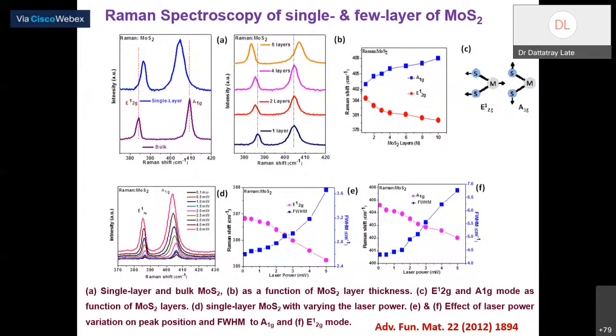So you can just do Raman spectroscopy of any sample, whether prepared by chemical method, by Scotch tape, by CVD, or any method. Find the difference between these two peaks. If it is 26, this is bulk. If it is less than 26, between 26 and 18 inverse centimeters, you can calibrate whether it is 1 layer, 2 layers, or in between. You can easily find out.